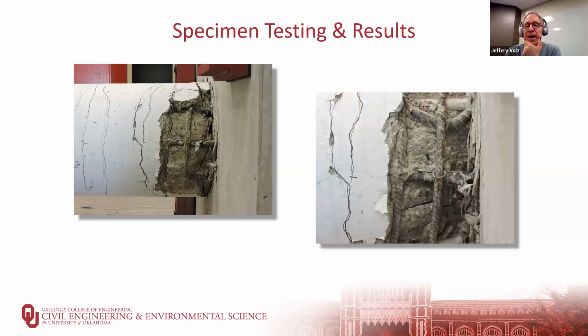And there you can see a close-up. Again, we've buckled this top bar, even though the spiral is there to prevent buckling, the concrete is there to prevent buckling. But as you put higher and higher cycles, you're going to start to rubbleize the concrete in the core. And so it provides less and less resistance to the longitudinal bars buckling.